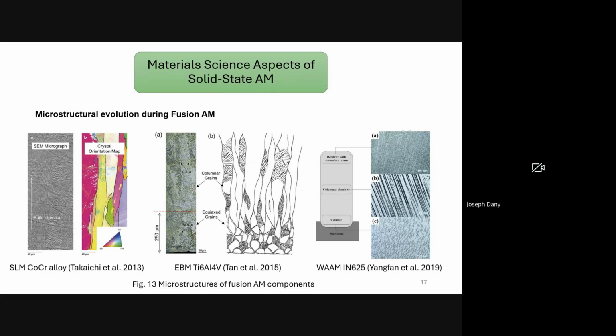Beyond microstructure, the fusion additive manufacturing process also leads to defects such as porosity from unmelted powder or trapped gases. Residual stresses from rapid thermal cycling and micro cracks all degrade mechanical performance, particularly fatigue life. Surface roughness from partially melted particles adds another fatigue stress concentrator. However, careful process parameter optimization and post-processing treatments like hot isostatic pressing (HIP) can mitigate many of these fusion-based issues.